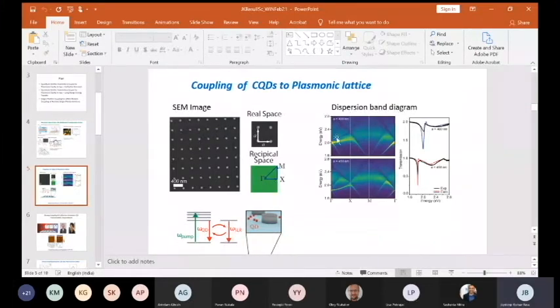And these have this nice dispersion, as you can see, the typical band structure in the optical regime. If you look at the transmission spectra, you can tune this extinction or the transmission spectra of these arrays by simply changing the dimensions of the lattice. What you see here is this broad feature, which comes from the individual metal cylinders. So you have silver here. If you chose some other material, this would shift. But this is very broad, and this is typical of all this type of metal particles and metallic nanostructures.